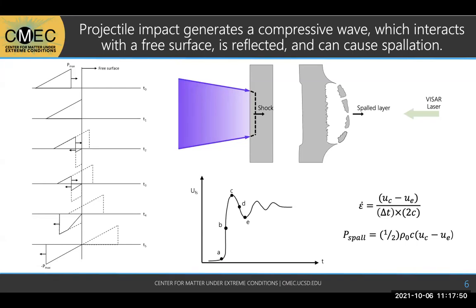What happens is, if you look at the drawing, that's showing just a simplified one spall scab flying off. But in reality, you actually have a bunch of these failing layers forming and opening within the material near that back surface. And so, if you imagine you have a bunch of these internal cracks, you have more and more of these wave reflections and interactions. And so that's why you end up with this weird, reverberating velocity curve. So from this curve, it actually tells us a lot of information.